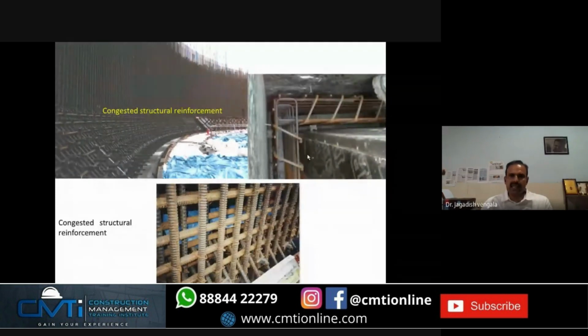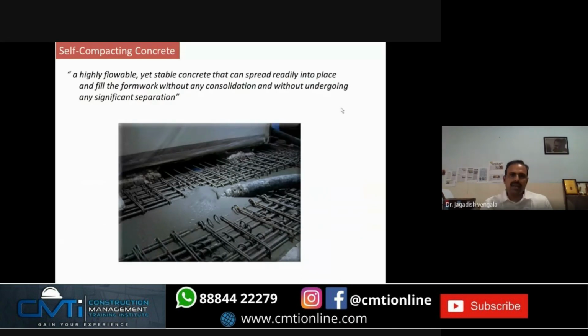But in case of congested structural reinforcement, there are a lot of problems. Even though you vibrate it, sometimes you cannot vibrate it in such situations. So in these situations, self-compacting concrete is one such solution. What is it? It is a highly flowable concrete. It flows, and even as it flows, it is stable at every place it flows. And it can spread readily into nooks and corners of the formwork. You have a bigger slab with a formwork. If you pour the SCC from one side, it flows and reaches the other corner with the same homogeneity, same stability, and it fills the formwork.